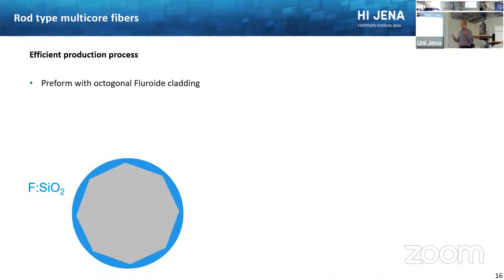And the most important part, of course, is the fiber itself. How do you create such a fiber with a lot of single cores? What's the production process? We worked here with our colleagues from the Fraunhofer Institute on that, and I think came up with a very efficient process. So we start here with a preform shown here at the bottom. This is fused silica, and there's another ring embedded, fluoride doped. It has a bit different refractive index, and this is basically guiding your pump light.